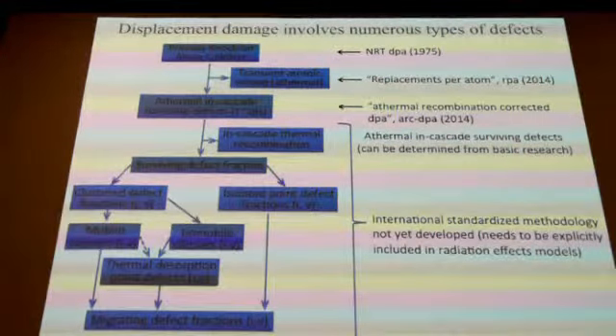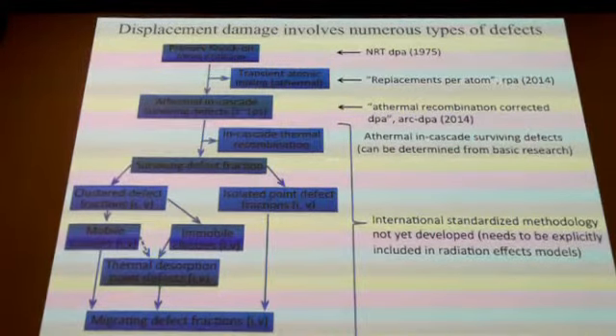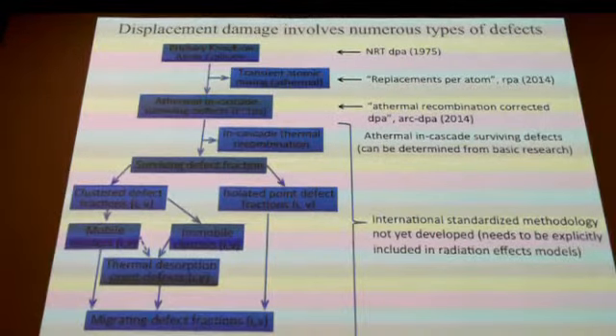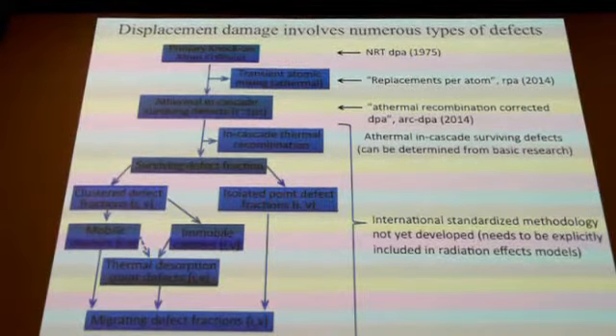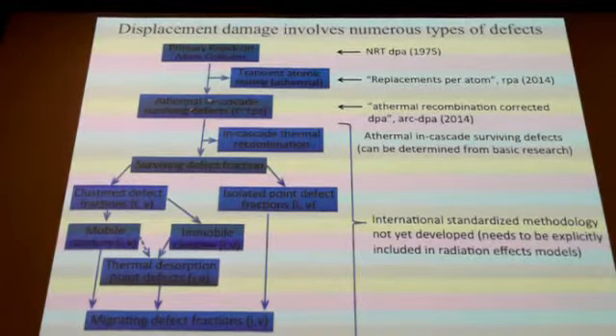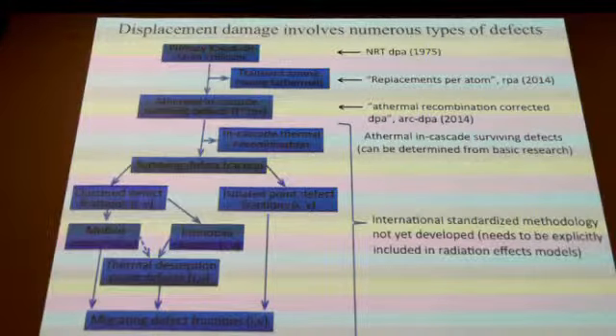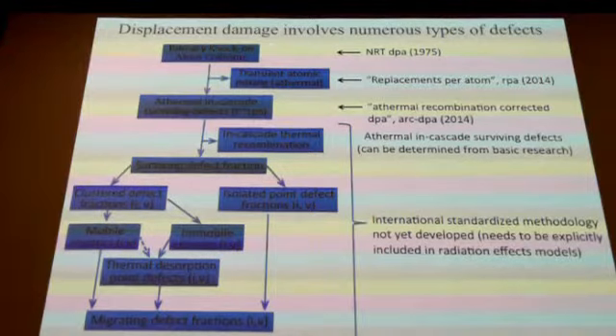So essentially, this is a flow chart, a logic chart of a sequence of events that happens when you have an initial atom being knocked off its lattice site. A bunch of things happen. You have some initial transient, temporary atomic mixing that occurs in the material. And then you get some additional recovery going on with that. And at the end of this process, you end up with some surviving defect fraction. So the NRT DPA did a pretty good job of calculating this.